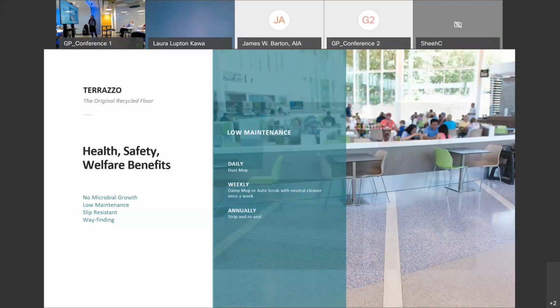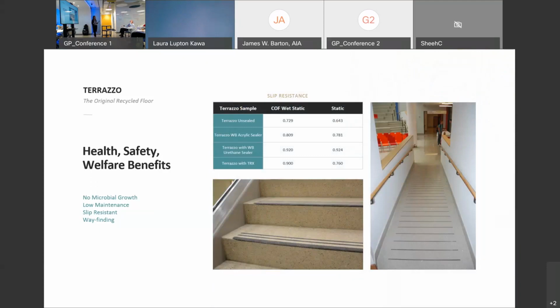When we are talking about slip resistance, that really is a function of how we are finishing it and what sealer we are using. That sealer on the surface is going to dictate the coefficient of friction. Manufacturers have all tested to the James machine in terms of non-skid to that 0.6 and 0.8 for ramps, that minimum. A number of sealer manufacturers have also started testing to the new ANSI 137.1 standard, measuring the dynamic coefficient of friction. So depending what direction you're moving, we can provide some sealer recommendations that fit those solutions.